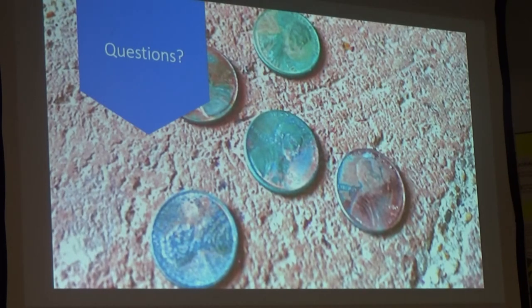If a coin is cleaned, someone would want to hide the cleaning by artificially coloring it. If you want to clean copper coins that are really ugly and you want to use them as circulation coins, make a dilute solution of vinegar — it has acetic acid and the coin will clean up fairly rapidly. Soda — Pepsi or Coca-Cola — will clean a really ugly oxidized surface and give you a nice clean copper surface. But as a collector, you don't want to do that with your collection coins.